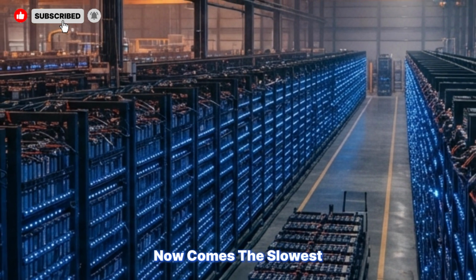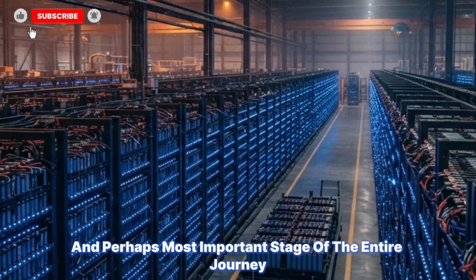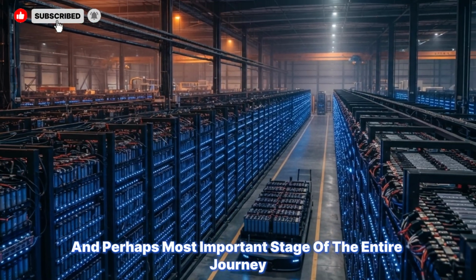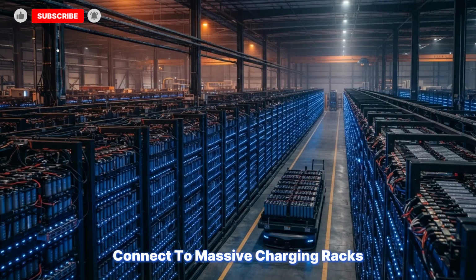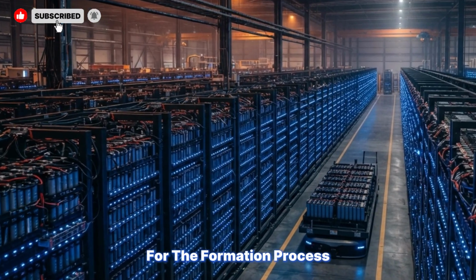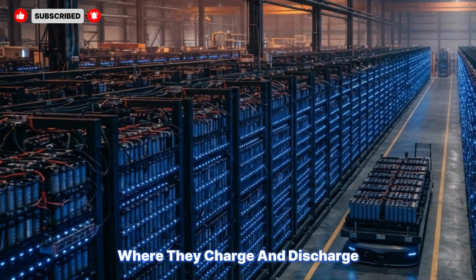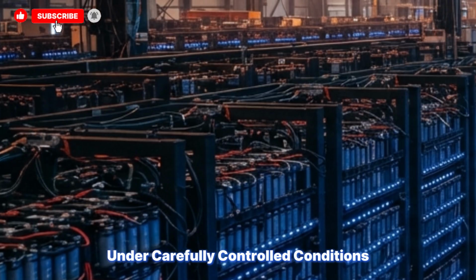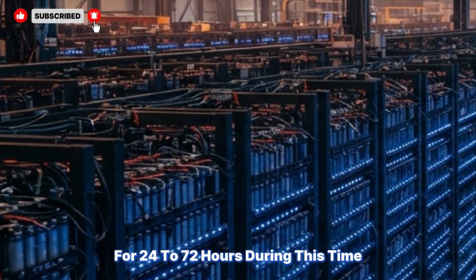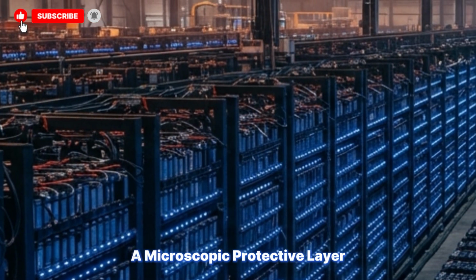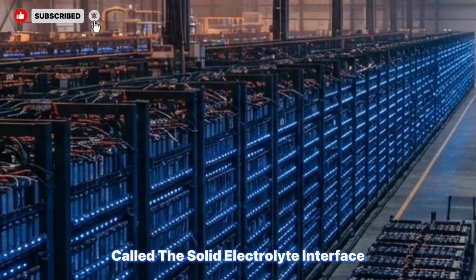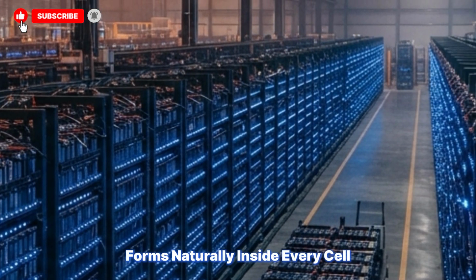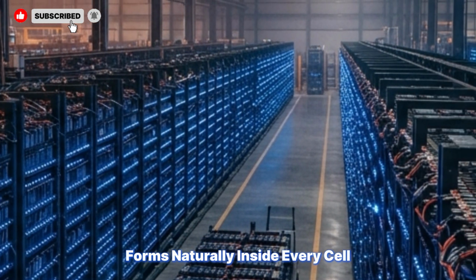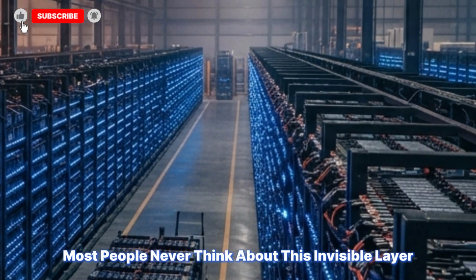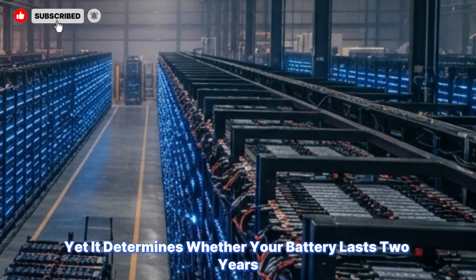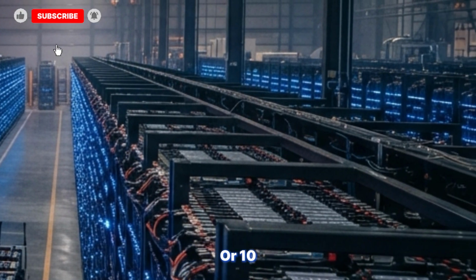Now comes the slowest and perhaps most important stage of the entire journey. Newly sealed batteries connect to massive charging racks for the formation process, where they charge and discharge under carefully controlled conditions for 24 to 72 hours. During this time, a microscopic protective layer called the solid electrolyte interface forms naturally inside every cell. Most people never think about this invisible layer, yet it determines whether your battery lasts 2 years or 10.